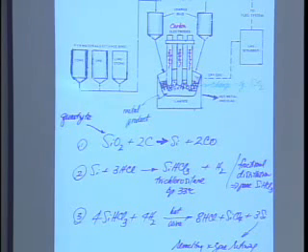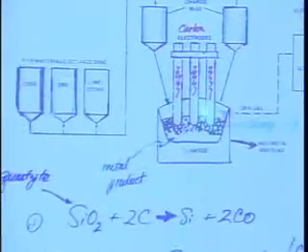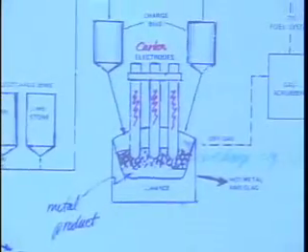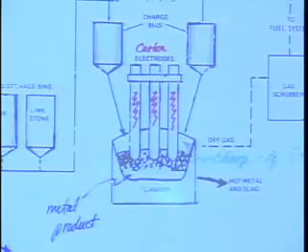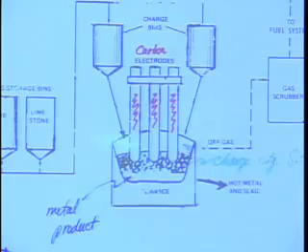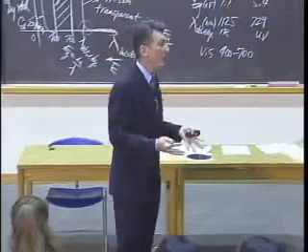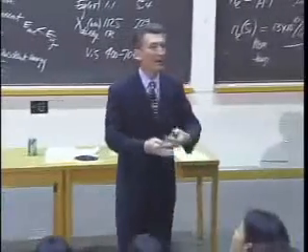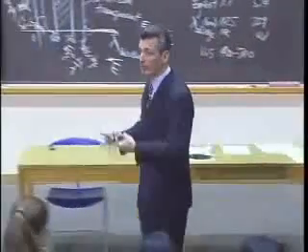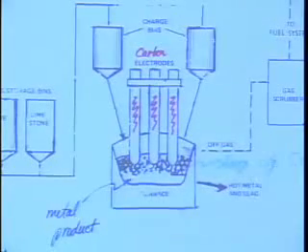And we take silica and we feed it into this furnace, which was invented by Siemens. It's an electric arc furnace. It has 3 carbon electrodes, and these are fed by AC power. And we put the sand in here with a few other ingredients, and the action of electric current passing between the electrodes actually melts the charge. So you have this liquid honey-like goo of silica and some other ingredients. And then the reaction proceeds.